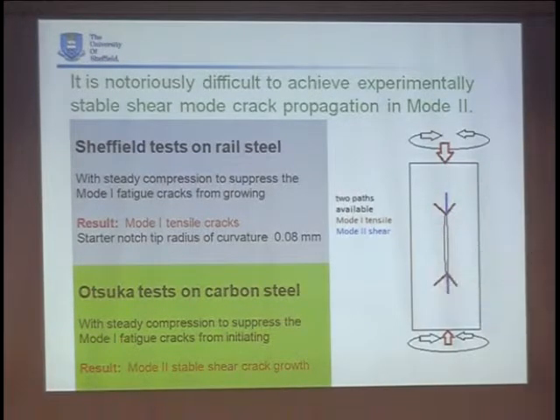Essentially, we had a tubular sample in a tension torsion machine, and we put in an axial crack, and under cyclic torsion, of course, that sees pure shear, and the Mode 2 crack should extend along these blue directions quite nicely. Very often, though, we find with pure torsion that the cracks will bifurcate on these red planes and grow in Mode 1 instead. Otsuka had the marvellous idea that you could put on a steady compression to close those incipient cracks, and then they wouldn't grow. And that would stabilise the Mode 2, and we could do some nice Mode 2 experiments.